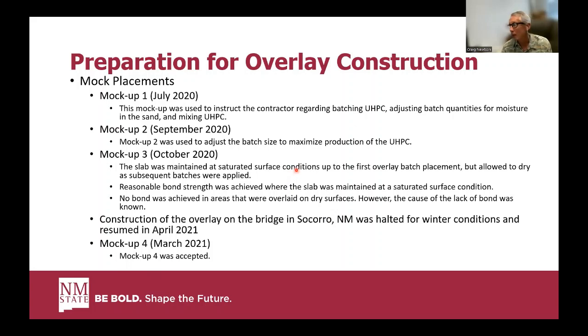We then went to, well, the project was let, and during the letting process, it was decided to enforce Buy America, which kind of forced us to change our steel fibers. Our steel fibers had at one point been produced in the United States, but that plant had shut down. The fibers that we wanted to use were now produced in China. Those were not going to be allowed, so we needed to perform some work to come up with a different fiber. In our case, Brad Weldon had an old mix design that he pulled out with a different fiber that was produced in the United States, and that was the fiber that we used as the replacement.